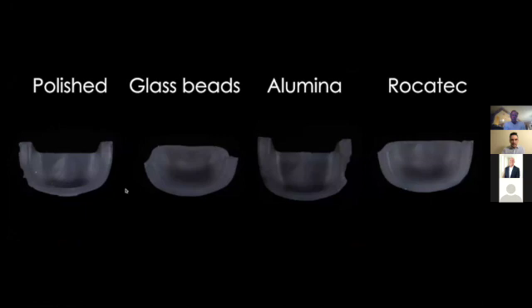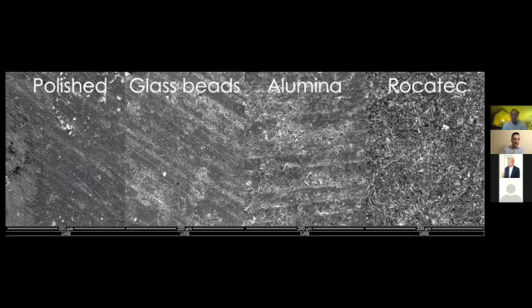Here's a bunch of different zirconia crowns. We cut them in half just to save some money. Then we looked at the control ones that were sandblasted with glass beads, with alumina particles, or with Rocatec. Rocatec and CoJet are the same thing. They're silica-coated alumina particles. We looked at the polished versus the glass beads versus alumina versus the Rocatec. Let's get a little higher magnification to make it easier to see.